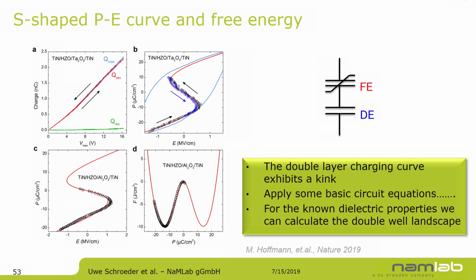The very interesting thing was that there's also no hysteresis effect. This only happens if you do the switching fast enough. It needs to be fast enough that there's no charge trapping into interfacial layers leading to a complete screening of your dipole. He could do this for the tantalum oxide and aluminum oxide case. And from this S-shaped curve, you can then calculate back, as I showed you in the beginning, the double well potential of your ferroelectric material.